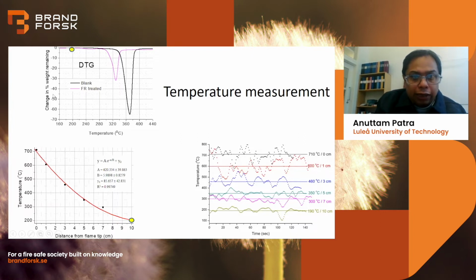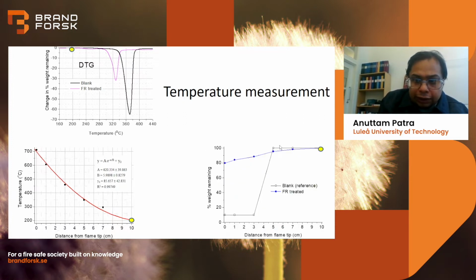So if we hang a cloth, I am showing you the differential thermogram for both untreated blank cotton and one of our flame retardant treated cotton. At 200 degrees, both have no effect. So if we plot, you can see there is no change.